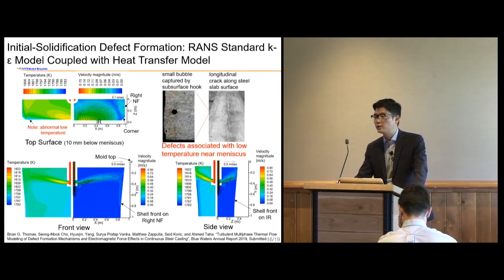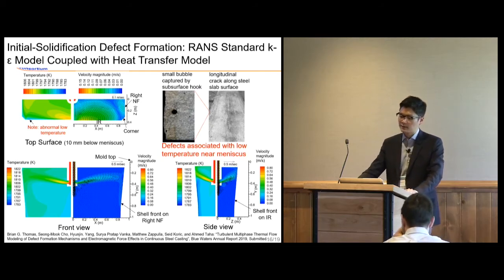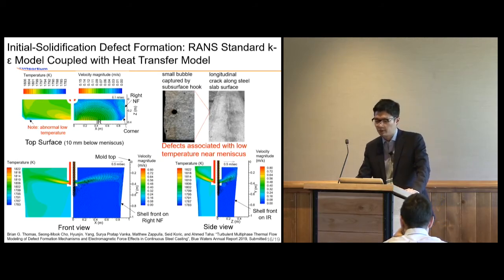We also investigated the initial solidification defects such as the meniscus freezing, the hook formation, and the longitudinal crack formation near the meniscus using the RANS-based thermal model coupled with the heat transfer model. We found that the distribution of the superheat flux around the mold perimeter can be very non-uniform due to the unoptimized mold flow pattern. In particular, superheat is unable to reach the meniscus corner region. This can lead to deep hooks and longitudinal crack formation.